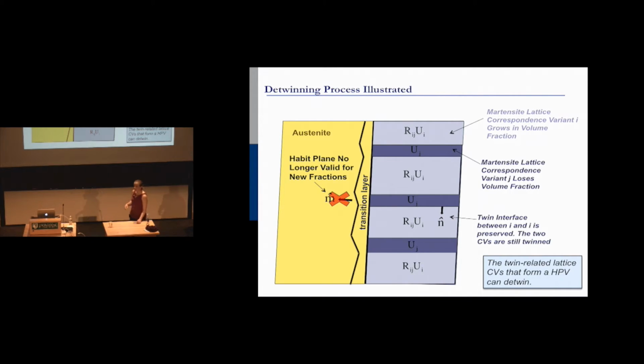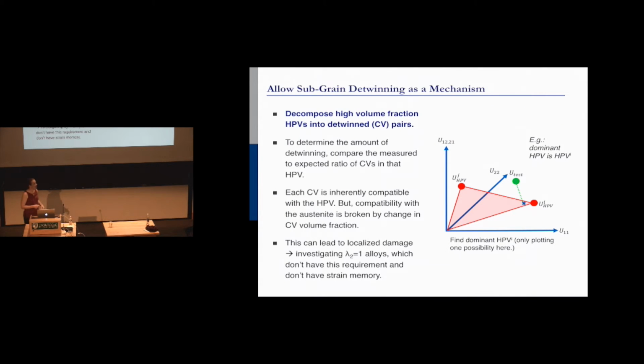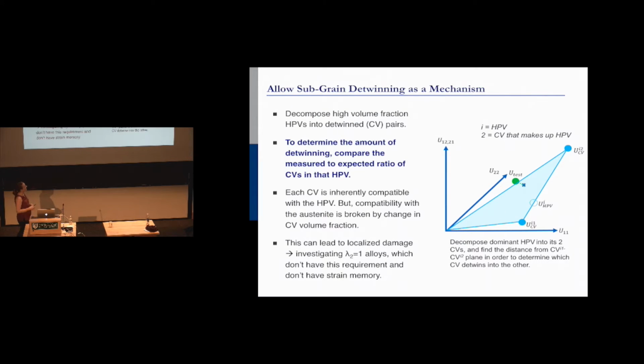Well, it turns out that if you allow this detwinning to happen, so you do the same type of plotting, but now you say we moved it to a transformation space. I won't go into that, but you basically are plotting the strains. And you now allow two of these possible habit plane variants, these layer cakes. You pick the one that has the most, and you allow it to break out into its two correspondence variant pairs. You're basically allowing one of the layers to grow at the expense of the other.